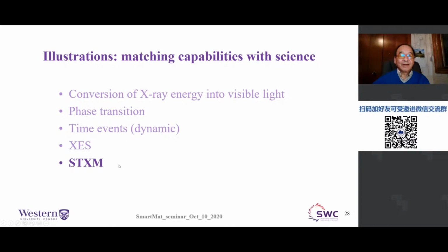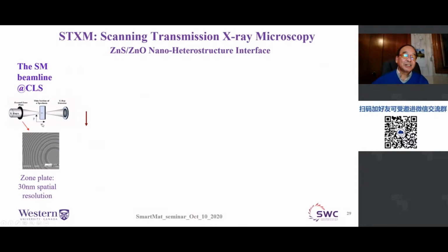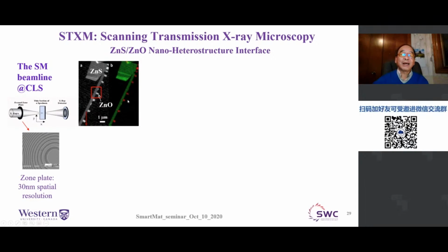Okay, so the last but not least item I want to talk about is scanning transmission X-ray microscopy. This technique takes advantage of the coherence of the undulator, and we can focus it with a zone plate onto a very tiny spot, right? At the SM beamline at CLS, they can typically go to 30 nanometers, but it can go smaller. Basically, just like any other spectroscopy, you're moving the sample across the beam, pixel by pixel. Let me show you some of the results that we look at.